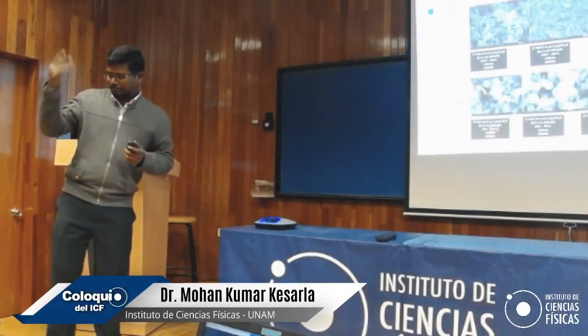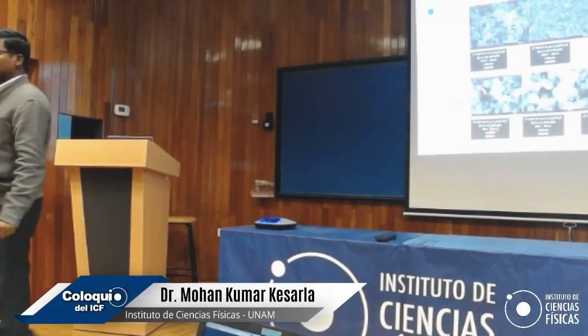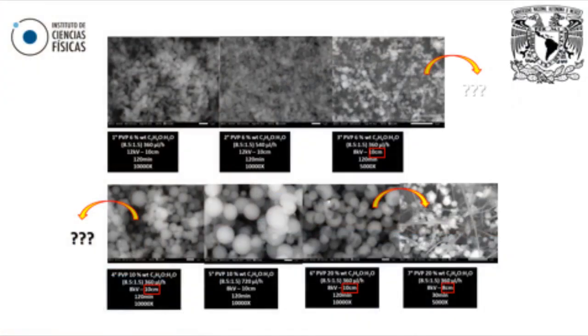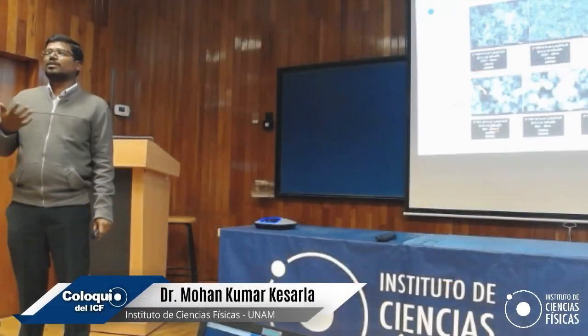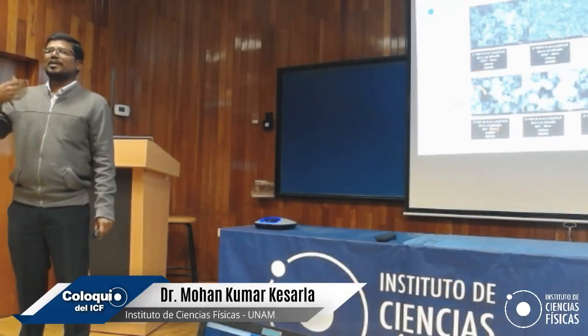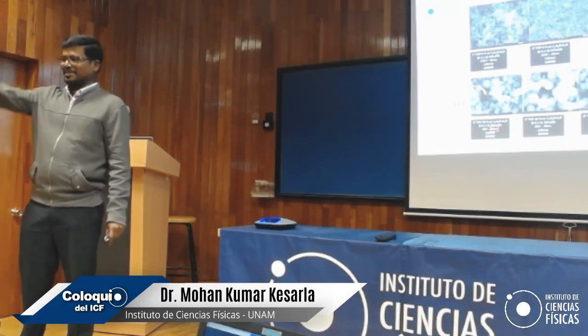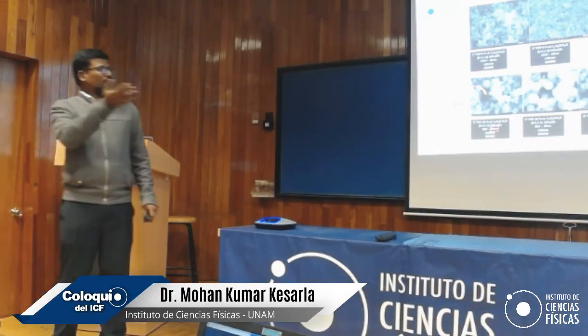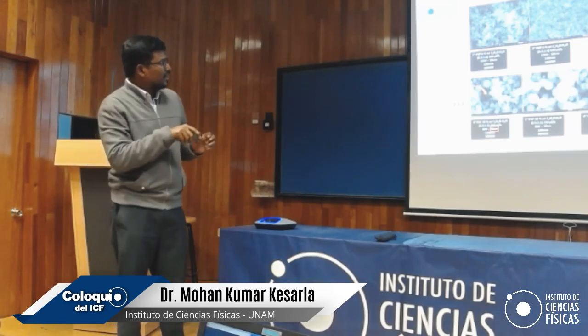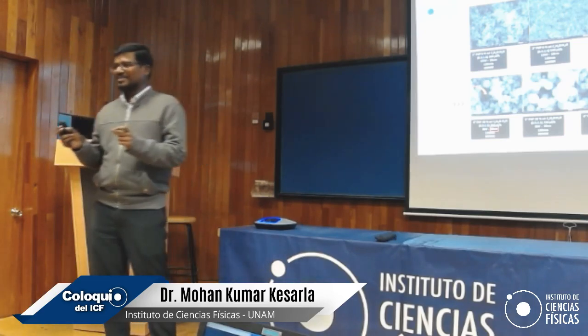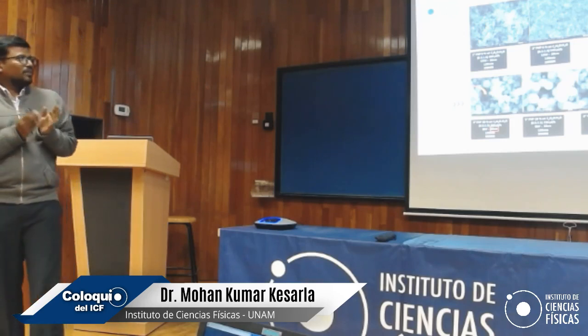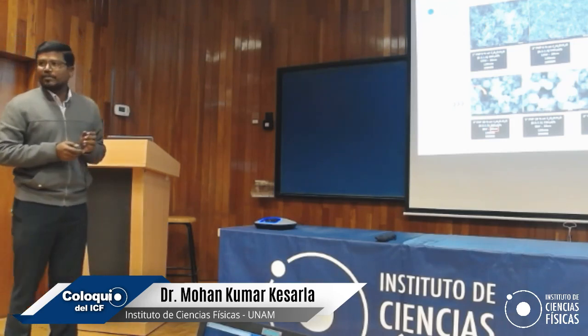This is one of the experiments done in our laboratory. Can you find any fibers there? There are no fibers. We actually tried for fibers, but what happened? Because of poor process parameter control, instead of getting electrospinning, we got electrospraying. So instead of getting fibers, we got polymeric nanoparticles. Here each and every parameter is very, very important.